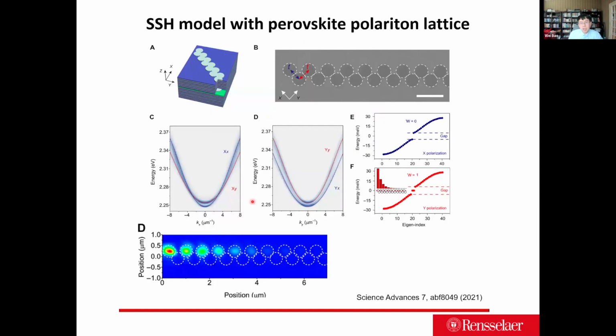I want to say that before people moved to the two-dimensional case, at room temperature there was also a perovskite endeavor using the orthorhombic phase, the birefringence of cesium lead bromide. One can automatically make the hopping between the two different. This is done by Professor Qihua Xiong's group, and Rui Su, where they can demonstrate this localized topological mode inside the bandgap.